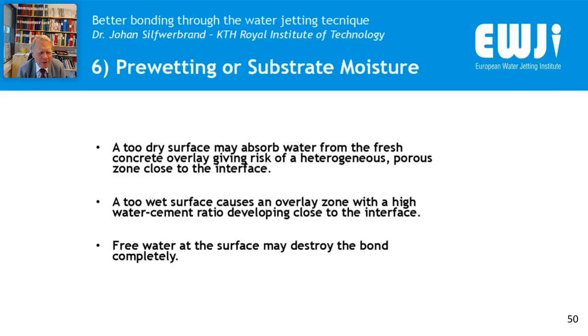One of the secondary factors is pre-wetting of the substrate moisture, and this is some reasoning. A too dry surface may absorb water from the fresh concrete overlay, giving risk of a heterogeneous porous zone close to the interface. And if you have a porous zone, you have a lower strength. A too wet surface, on the other hand, causes an overlay zone with a high water-cement ratio, and a high water-cement ratio leads to a low strength. And then there is a risk that you will have a poor interface, and that is not promoting a good bond. And then free water at the surface may destroy the bond completely.